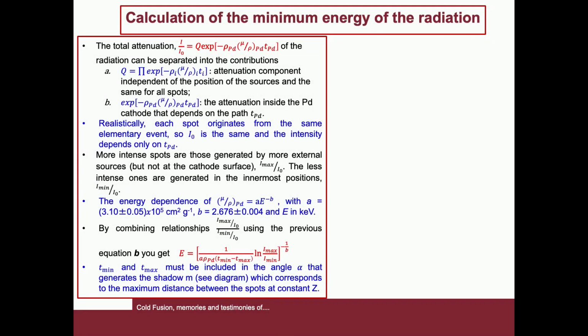Calculation of the minimum energy of the radiation. The total attenuation is given by this relationship in red. The total radiation attenuation can be separated into the contributions A and B. A is the component of the attenuation independent of the position of the sources and is the same for all spots. B is the attenuation inside the palladium cathode, which depends on the radiation path in the palladium itself.